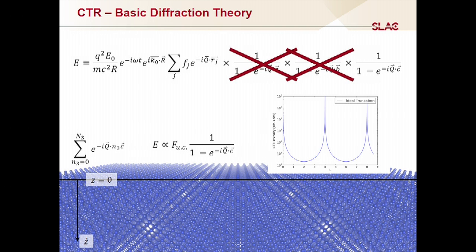And basically, because I'm going from basically nothing to a continuous number of unit cells, my scattering is going to look like the scattering from a single unit cell times this factor. And if you look at what that is, you get these big dips away from the Bragg peaks, and then you get these big things where you should have a Bragg peak. So this is now L in the HKL Miller indices.